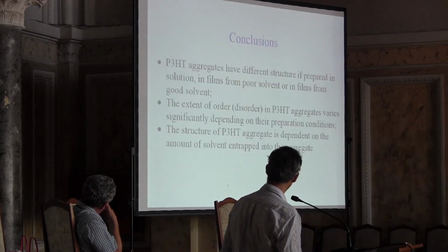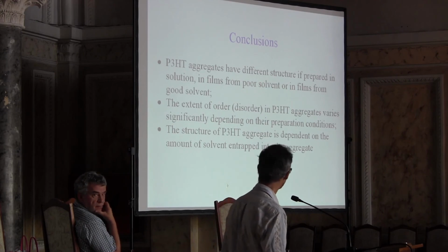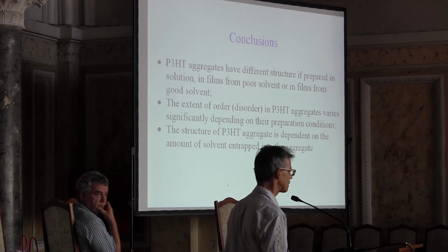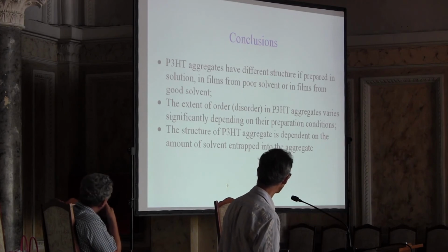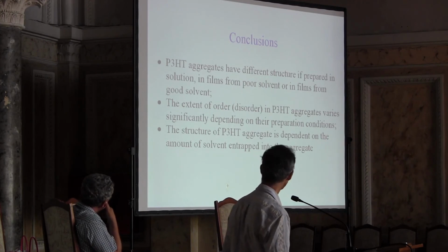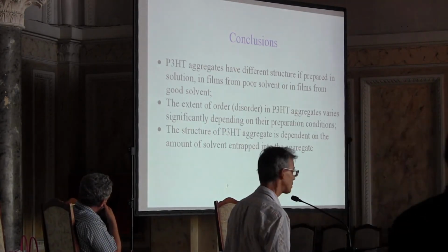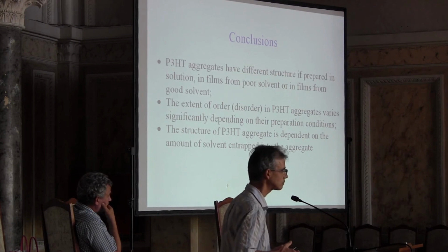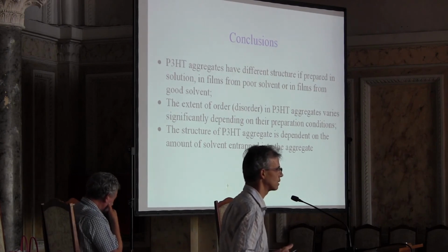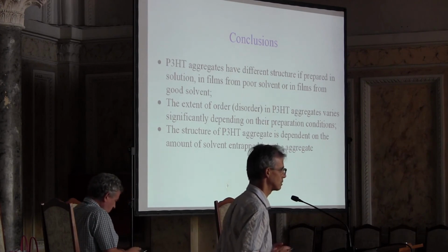So, in conclusion, I tried to show you that polythiophene aggregates have different structure depending on preparation conditions, whether we prepare it in solution or in films, with different solvents, and the extent of ordering or disordering in polythiophene aggregates varies depending on the preparation conditions, and also the structure of the aggregates can be controlled by a different amount of solvent entrapped in the aggregate.